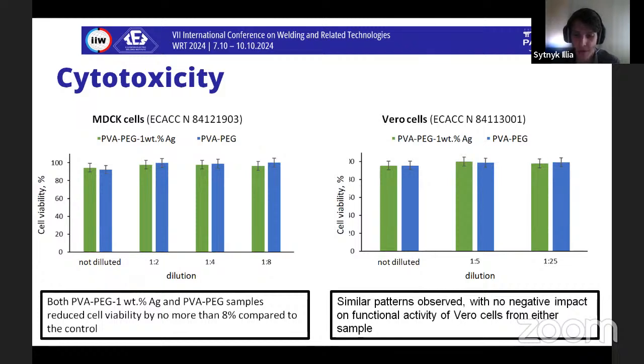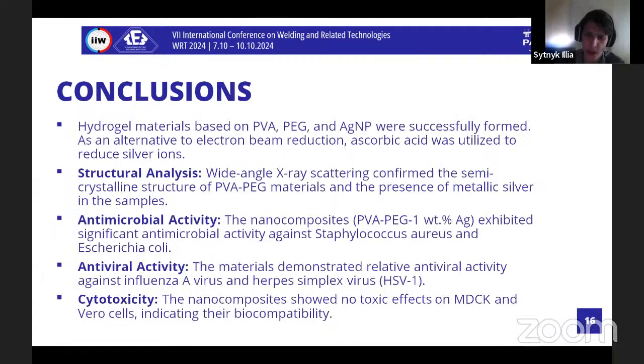When examining the toxic effect of the samples on the Vero cell culture, similar patterns were revealed as on the MDCK culture. That is, samples with silver and without silver did not have any negative effect on the functional activity of Vero cells. As a result of the research, hydrogel polymer nanocomposite materials based on polyvinyl alcohol, polyethylene glycol, and silver nanoparticles were formed. As an alternative to electron beam reduction, ascorbic acid was utilized to reduce silver ions to nanoparticles, allowing for hydrogel cross-linking at a lower dose.